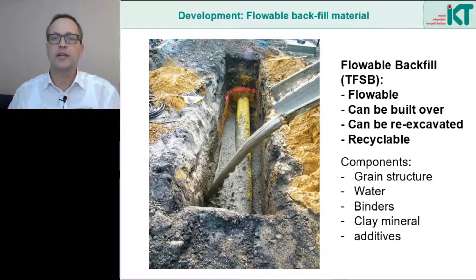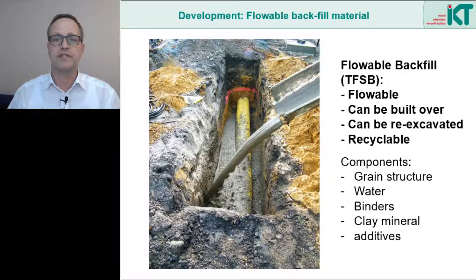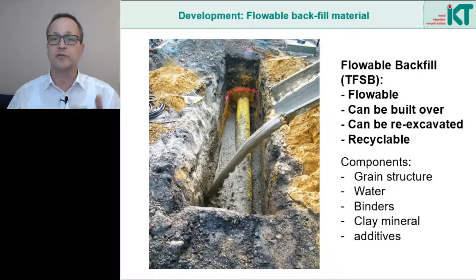Here we see the use of a flowable backfill, also called liquid soil, to embed a gas pipeline. The technical term for these materials is temporarily flowable self-compacting backfill materials, or TFSB. That means the material is liquid when installed and can flow completely around the pipeline. The material then hardens and can finally be built over. Over the course of its service life, however, this kind of material must not harden too much, as it should easily be re-excavated, for example for later connections or repairs.